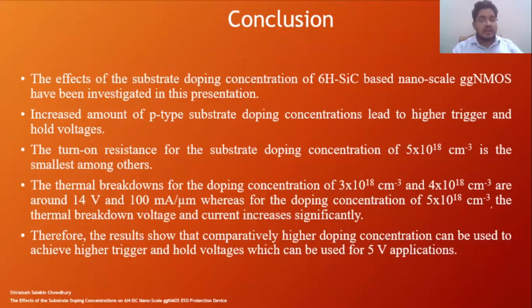It is found that an increased amount of p-type substrate concentration can lead to higher trigger and hold voltage of 6H silicon carbide devices. The turn-on resistance for the substrate doping concentration of 5E18 per cm cube is the smallest among other substrate doping concentrations, resulting in better voltage clamping performance and improved current handling ability.